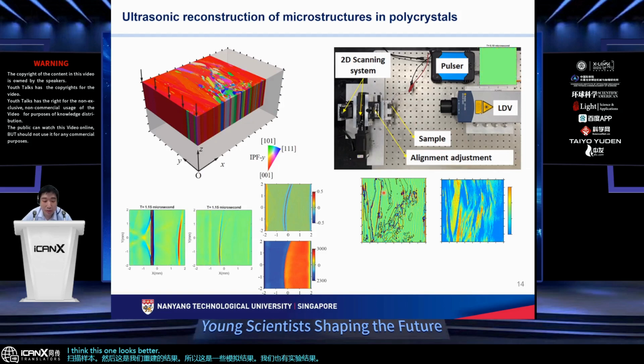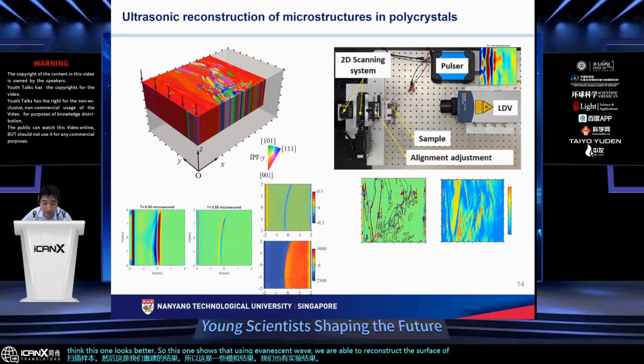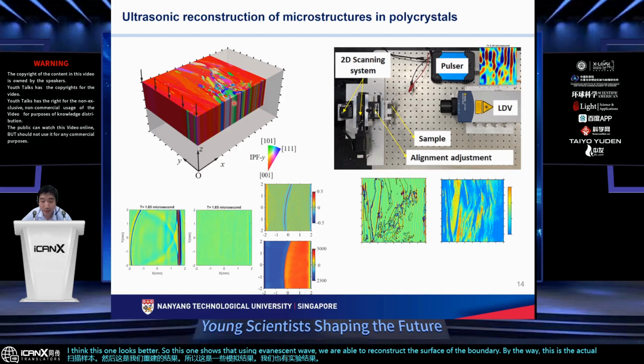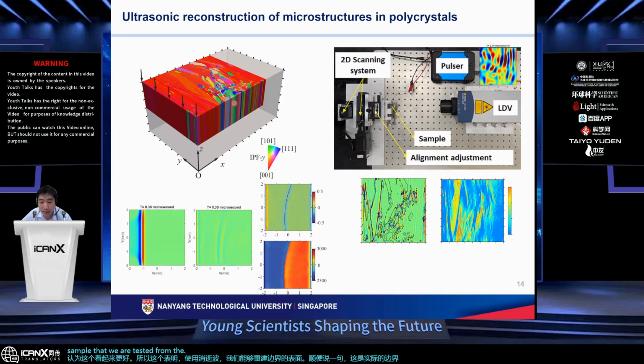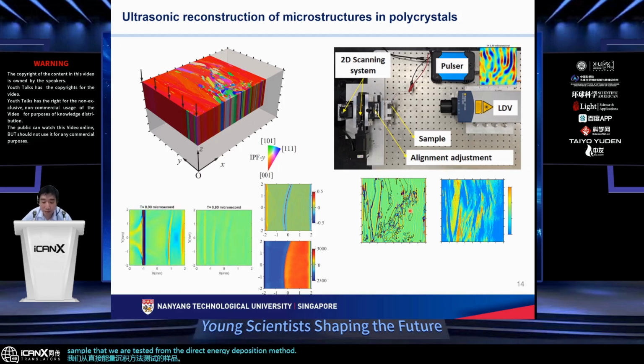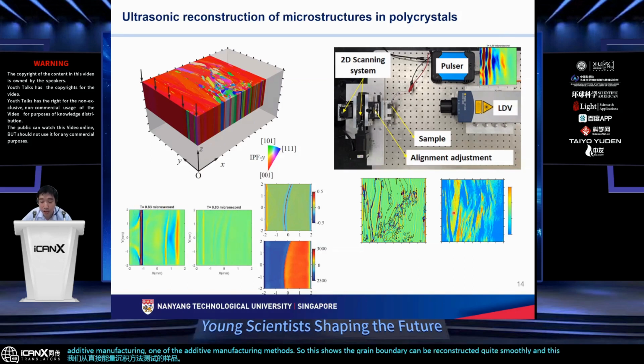So this one shows that using the evanescent wave, we are able to reconstruct the boundary. By the way, this is the actual boundary of a sample that we tested, made by direct energy deposition, one of the additive manufacturing methods. So this shows the grain boundary can be reconstructed quite smoothly, and this image shows the velocity can be reconstructed in a reasonably good way.